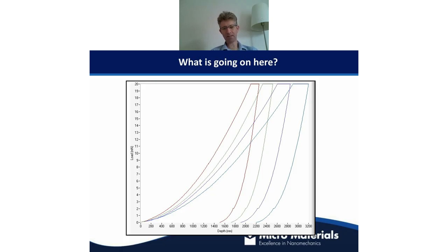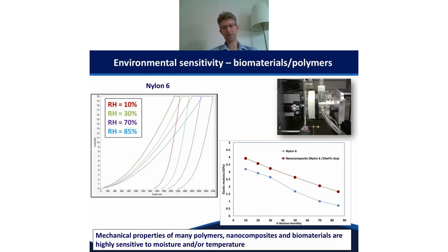What's actually happened is that the customer has changed the test environment between doing those different tests. They've changed the humidity in the test environment. The relative humidity has been changed from 85%, which is this blue one here, then to 70% in this curve, then to 30%, and then right down to the lowest humidity, very, very dry at 10% for the red curve.